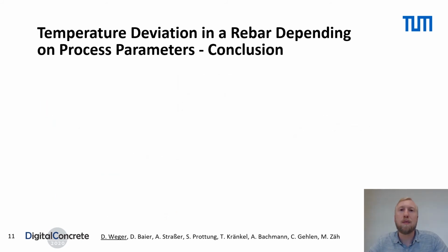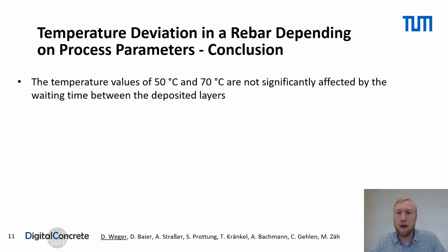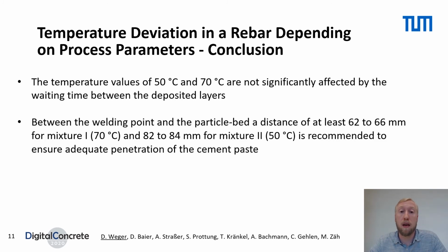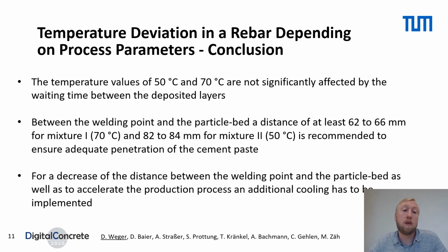Let us now conclude the main results of the temperature deviation measurements. The first point is that the temperature values of 50 degrees Celsius and 70 degrees Celsius are not significantly affected by the waiting time between the deposited layers, and between the welding point and the particle bed, a distance of at least 62 to 66 mm for mixture 1 and 82 to 84 mm for mixture 2 is recommended to ensure adequate penetration of the cement paste. However, for a decrease of the distance between the welding point and the particle bed, as well as to accelerate the production process, an additional cooling has to be implemented.